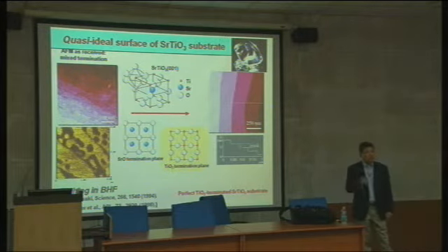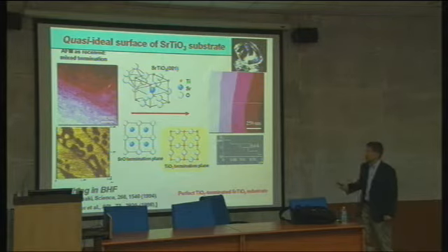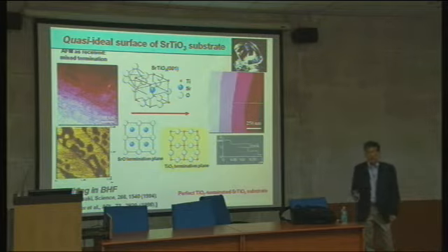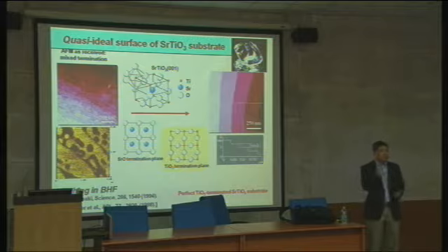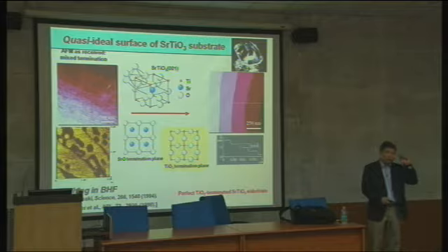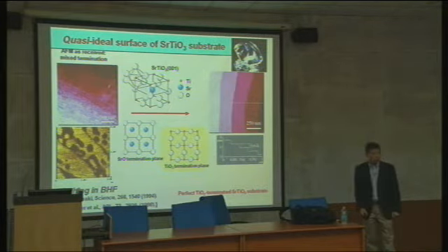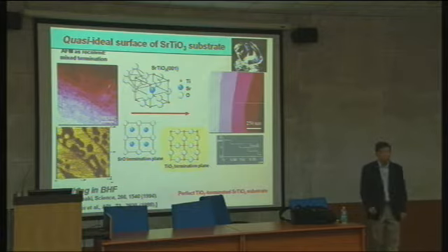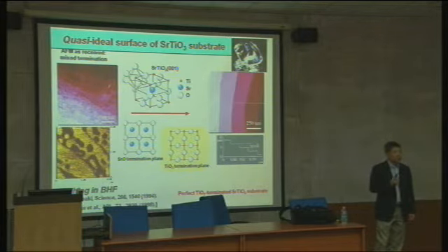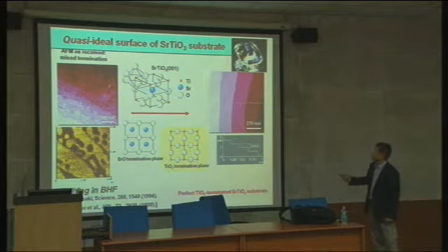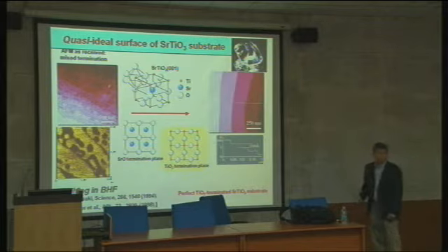The basic background of this is very simple chemistry, because strontium is more basic than TiO2. Okay? So your strontium layer is a somewhat basic layer, which means it can easily dissolve in acid. But you don't want to use a very strong acid. If you put in a strong acid, it will dissolve everything. But there's some kind of borderline: a very, very weak acid can preferentially attack only the strontium oxide layer, not the TiO2 layer. So that is a buffered HF, buffered hydrofluoric acid, very dilute. That only attacks the strontium oxide layer, and then you can create a beautiful single surface termination.